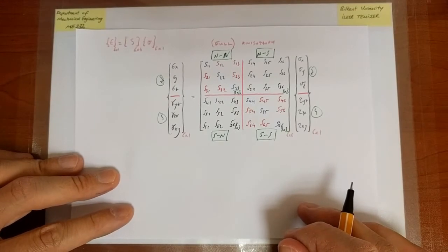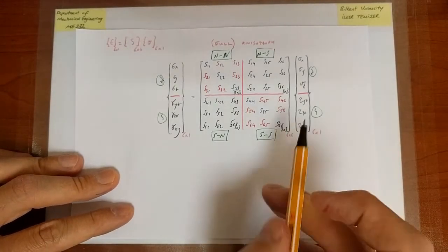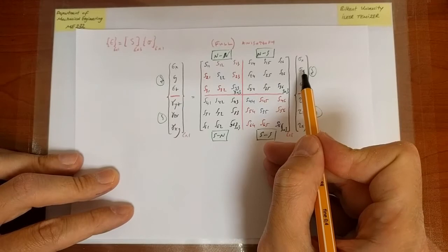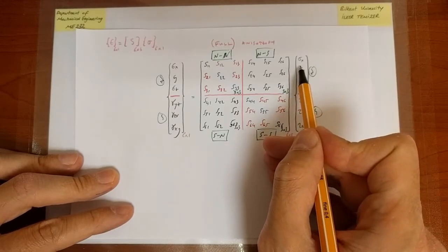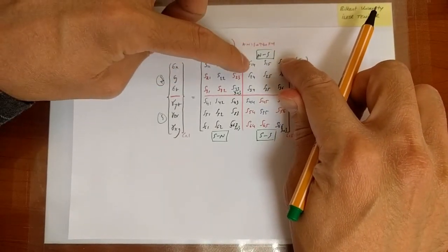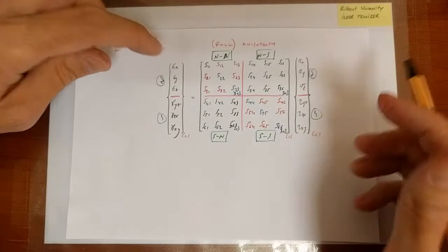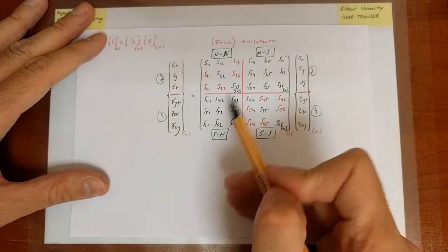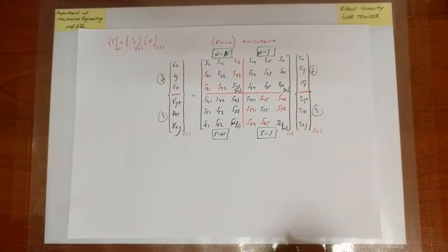Okay. So now what we see is, suppose you have a scenario where you have only shear stresses and no normal stresses. These are 0. These would multiply, for instance, the first row, and these are non-zero, and hence you would get a normal strain out of it, etc. So the fact that you have these eventually causes that behavior that is distinct from the case of isotropy.